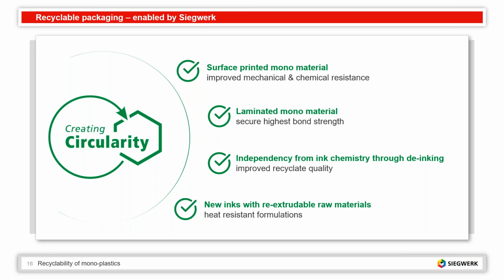In my part, I have pointed out that we as Siegwerk see a significant benefit in de-inking, and with our de-inkable solutions, we can contribute together with you to an improved recyclate quality, because we can get rid of all the ink components. But since this will still take some time until this can be established in the industry, rather short term, we can also offer inks with a higher heat resistance, with a target that they are re-extrudable, using re-extrudable raw materials, like I have outlined on the last chart primarily.